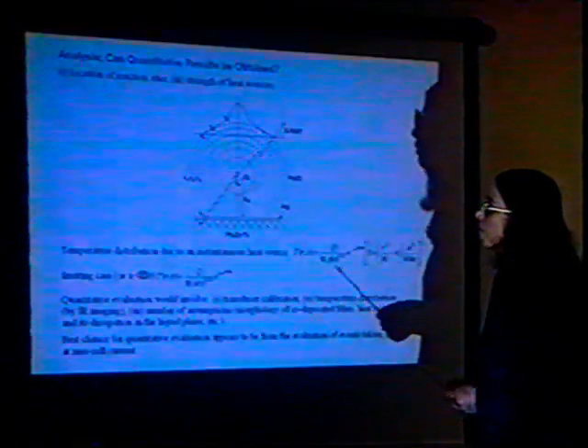Another thing we're working on is, can we quantitate the results we obtain with our piezoelectric crystal? And in particular, can we say something about the location of the reaction sites as well as the strength of the heat source? And this is the model we're looking at. Here's our piezoelectric crystal. We are assuming that our heat source has a spherical volume of radius A. And we have our heat source, which radiates out, and you get this thermal wave as a function of R.